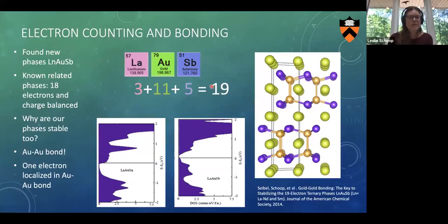But then we were looking at the crystal structure, and once we solved it, and thinking about it helped us solve it, we realized what is happening in this material is that the gold atoms come into very close contact with each other. Because they're in this close contact, they can form a chemical bond between these two gold atoms, which then takes one electron per gold and moves it down in energy. So think about it as a hydrogen model where you have two hydrogens with one electron each and they form a molecule. So therefore they're not open shell anymore, right? They don't have a single unpaired electron that could make it magnetic or flow around. And so this is what's happening here. There's a bond formed between gold atoms.